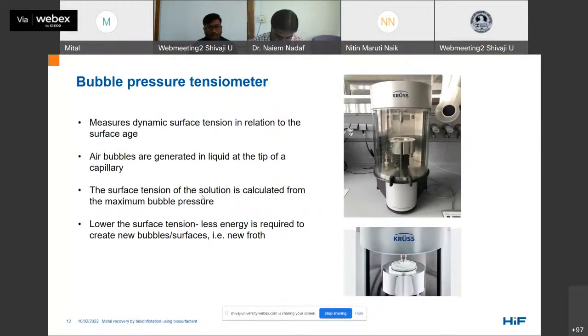So the main study again was the surface tension studies. It was studied using a bubble pressure tensiometer, which is an instrument to measure the surface tension, and it measures the dynamic surface tension in relation to the surface age. That is, you can see here, the air bubbles are generated at the tip of the capillary in the liquid, and the surface tension of the solution is calculated from the maximum bubble pressure required to form the new surfaces. So, lower the surface tension, less is the energy required to create new bubbles or surfaces, and in our case, new froth or new foam.